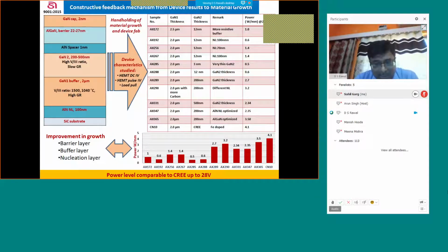Another important aspect I would like to discuss from our own experience is that just by saying my material is good, measuring only sheet carrier density and mobility is not enough, because until the complete device is fabricated and characterized for RF performance, I cannot say that my material is good. So initially we worked with this kind of practice, but a lot of experimentation was carried out with not so good results.